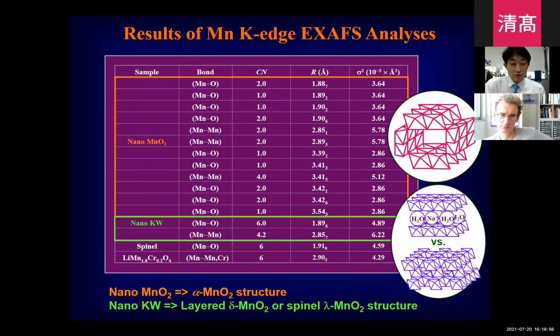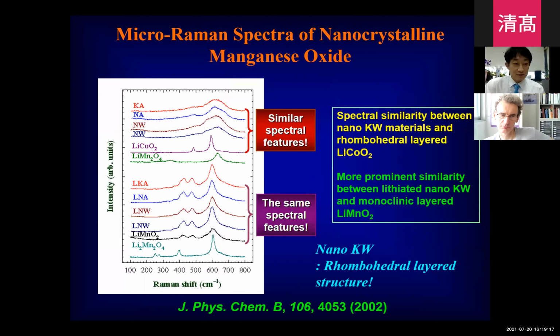But the problem is the nano KW. The XAS spectrum of this material can be fit with the edge sharing structure, but we cannot determine whether this structure corresponds to the layer type or spinel type, because both structures are composed of edge sharing. So we apply Raman. LiCoO2 is the reference spectrum for layered metal oxide, but LiMn2O4 is the reference spectrum for spinel. So if you compare the Raman features, due to the amorphous nature of this nanocrystal, the Raman spectrum is somewhat broad, but we can easily recognize the structure.